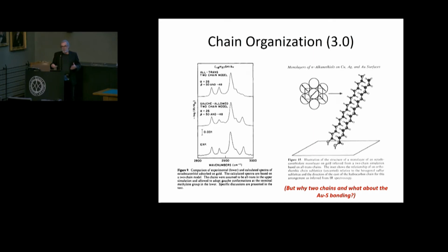And there's more that comes to it as well, and here's a lot of what I will leap through, just bypassing all the hard parts that went into doing this. But we find that there was a corresponding registry, at least in the simplest measurement that we did, that's showing this overlay of sulfur atoms in chains on top of the hexagonal lattice of a gold 111 substrate.